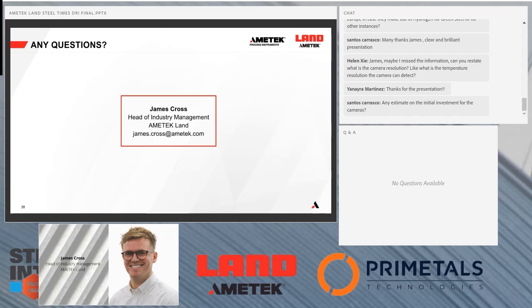I always compare the kind of temperature measurement on these heaters to measuring your weight. You don't really care what your exact weight is. There's no academic reason to understand your exact weight, but you like to know if you're getting too heavy or otherwise. So what we're really interested in with imaging is not absolute academic accurate temperatures. We're really interested in measuring changes, rate of change, and then if we're getting over those critical temperatures.